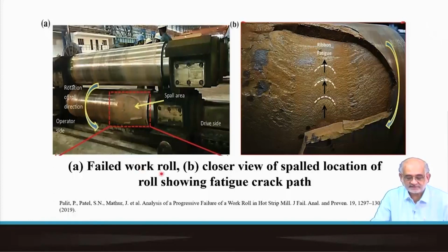And the main reason for this kind of failure is fatigue crack growth. As you can see here, just below the cracked region, which actually separated from the surface, just below that separated chunk, you see very textbook-like striations growing gradually from one end where the crack initiated into the surface. And this is typically called ribbon fatigue, which happens almost like radially propagating striation lines moving towards the other end of the surface. And eventually, when the plasticity of the material cannot withstand these stresses developing inside anymore, then the whole chunk leads to completely brittle or sudden failure.